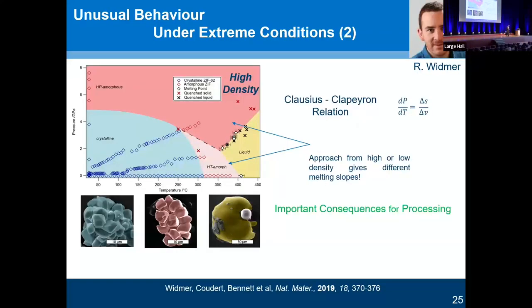But we can play around with that and we can stop recrystallization with heating. So instead, we just go from a crystalline system to a high temperature amorphous one to melting straight away, right? No collapse into a dense state. That gives us really interesting behavior because now we're going from open MOF, metastable, right? This is why I talked about the diagrams overleaf as being phase diagrams, because it isn't the thermodynamically stable phase. MOFs are all metastable because when we make them, they have solvent in, we remove the solvent, it's not the same material. So we can do this.